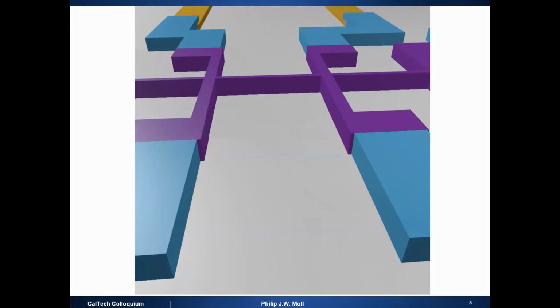It really depends. Our workflow is very different from that of layered lithography because we make the structures in free space. And when they're done, we place them on the substrate. That actually is very important because it helps us minimize or tune the stress between the substrate and the sample at will. And that's very important if we want to utilize strain or if we want to eliminate strain for the physics that's at hand, right? So right now I'm just talking about shaping.